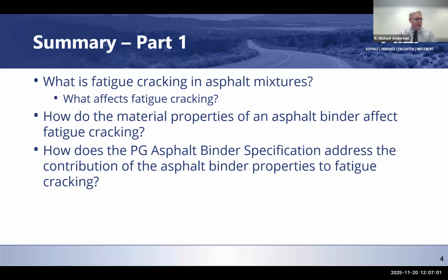So when we talk about fatigue cracking, what do we mean? It's repeated loading from traffic that results in longitudinal or alligator cracking. That's what most often we see. It's when tensile strain at the bottom of an asphalt layer exceeds the strength of the mixture and the cracking propagates to the surface. That's what we call classical bottom-up fatigue cracking.